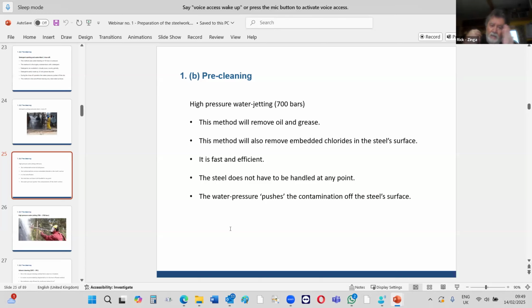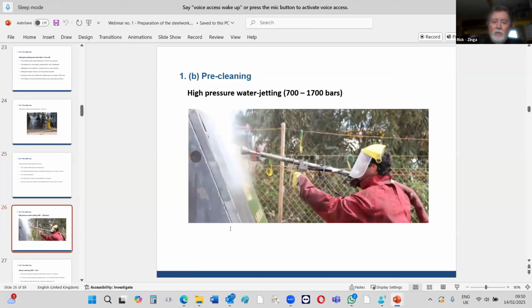It's the pressure. The energy from the water hitting that steel at 700 bars or above actually heats up the metal by about 3 degrees centigrade. And the metal, microscopically, actually opens up, and the water is forcing out all the salt, all the chlorides. So you won't have any contamination on the steel at 700 bars. So that's how it looks, the special nozzle. And you have to always wear gloves, although the only dangerous part is the first 100, 120 millimeters. After that, there's no danger from the pressure at all.